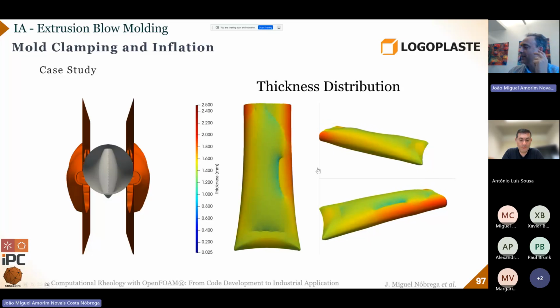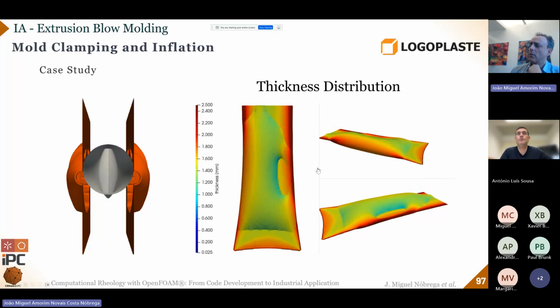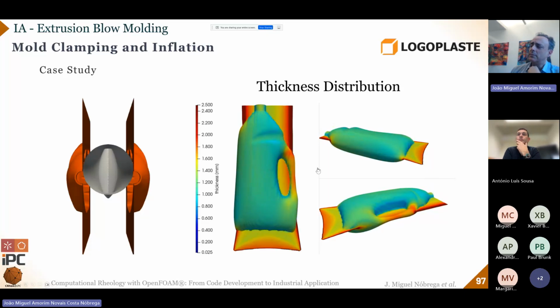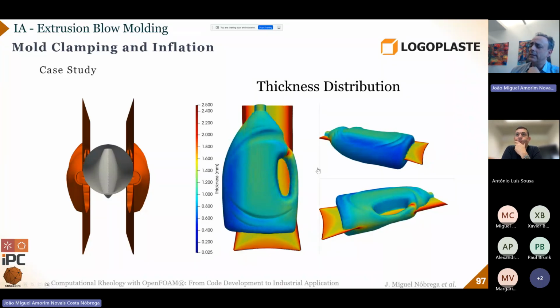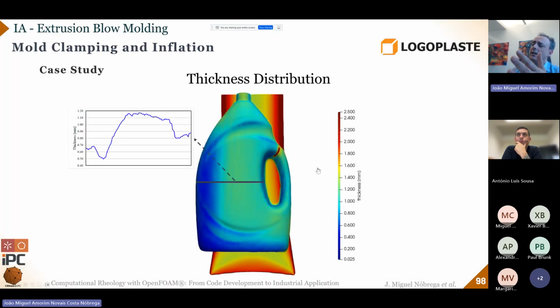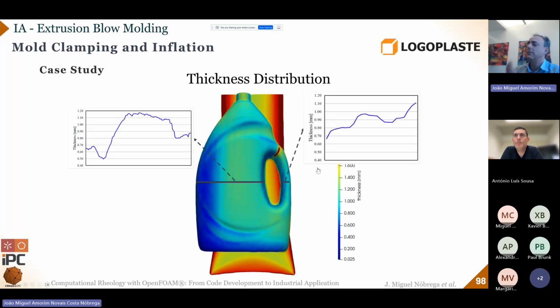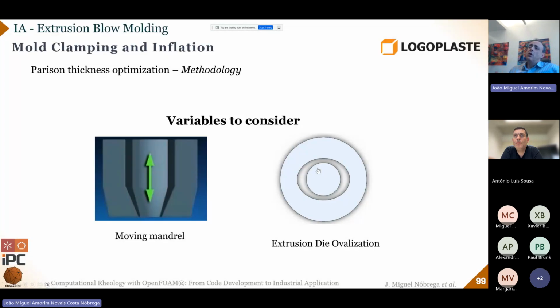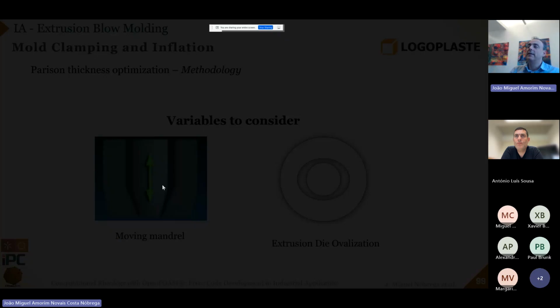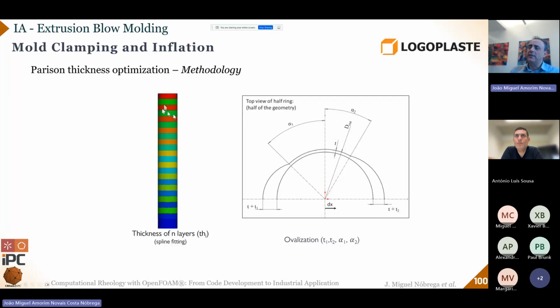So the mold is closing, and then it's blown, and we get the final container. By doing this, we can monitor, for instance, the thickness distribution and proceed accordingly in order to correct. What do I mean by proceeding accordingly? When manufacturing the tube, it's possible to have a tube with different thicknesses along the length.